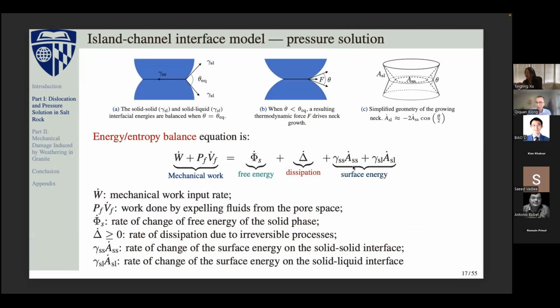So in this equation, you can see that we consider that the mechanical work input to this system, or to the contact, will equal three terms. The first one is the solid free energy change. The second one is the dissipation, and the third one is the surface energy change, because of the solid trapped in the contact, and the solid to solid surface and solid to liquid surface will change.